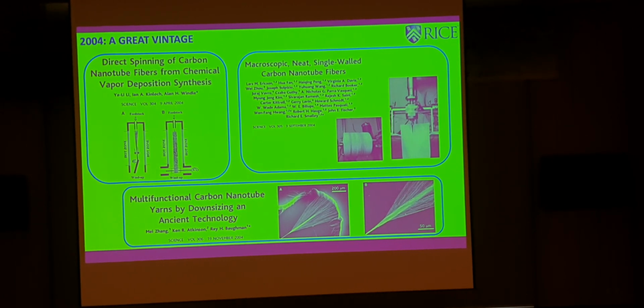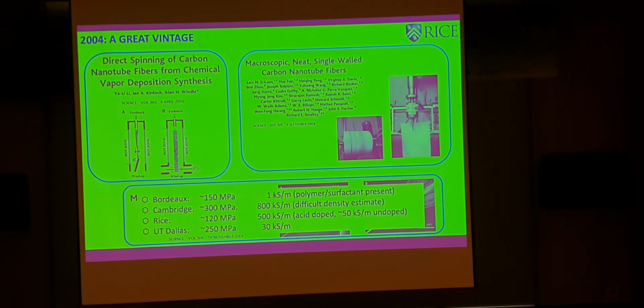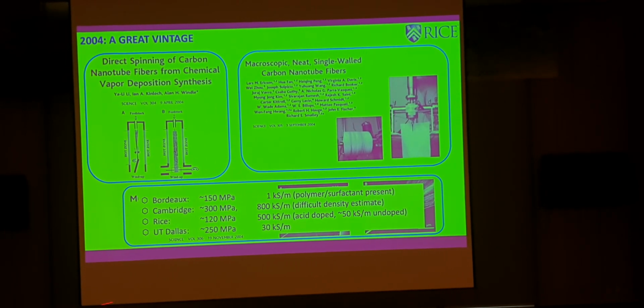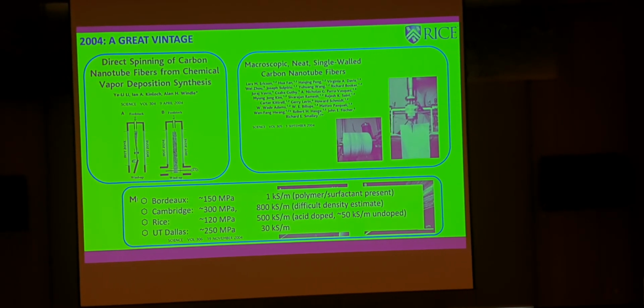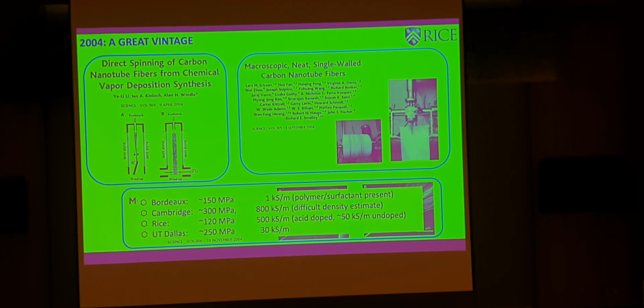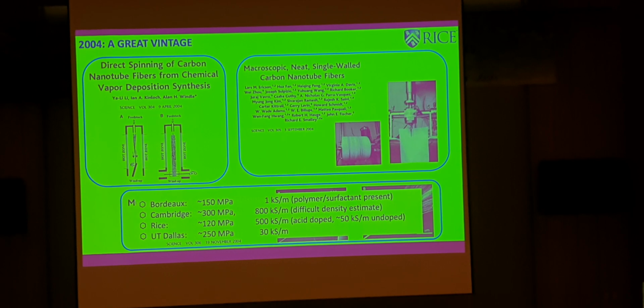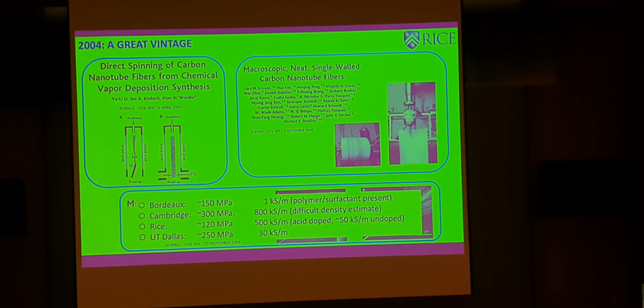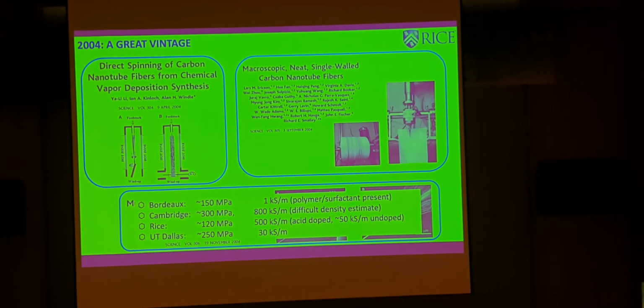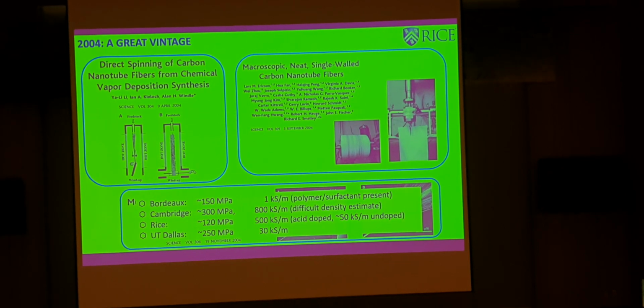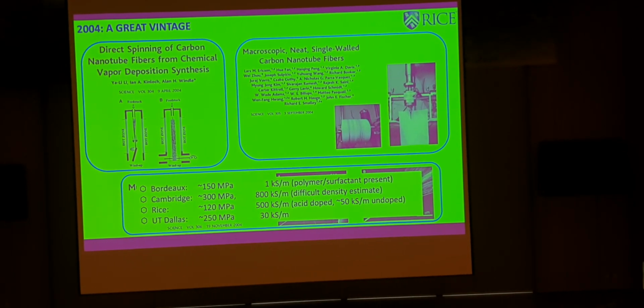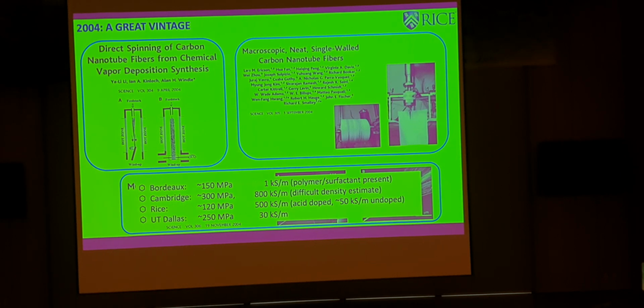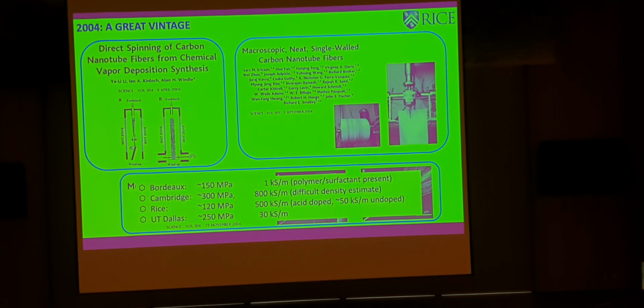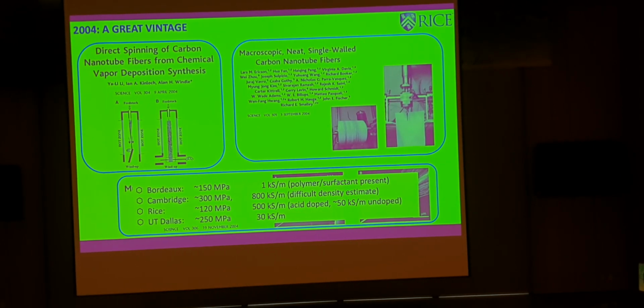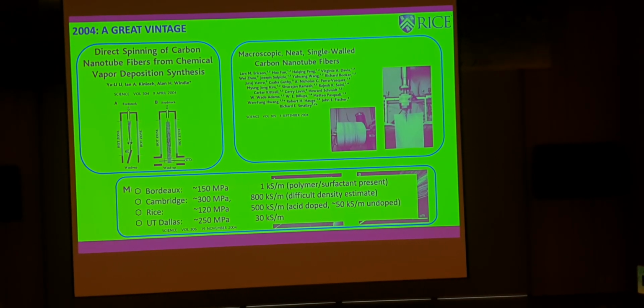One thing that's very interesting, if you go back to these papers and parse through the properties, is that they're not that different, right? The strength is within a factor of 2, really, and the conductivity is a little bit more broad, but now we know that these were doped, right? And there was some residual acid. The Cambridge material was really difficult to measure the density of at the time, so maybe this was the right number, maybe it was not quite the right number, but again, within an order of magnitude, right? And certainly not even within an order of magnitude of what I had in my first slide, right? So very, very far from these ideal projections. So it was a bit of a bummer.